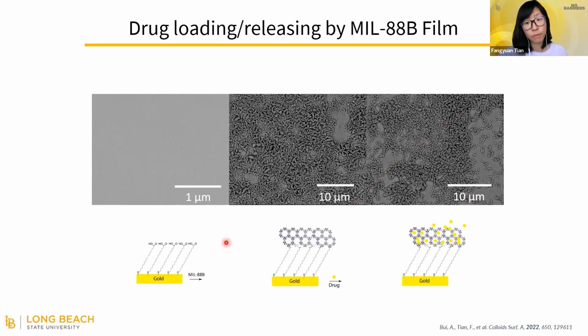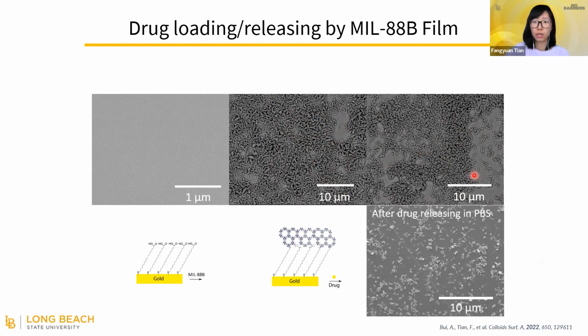We also used scanning electron microscopy to look at the morphology of the surface after each modification step, starting from the self-assembled monolayer coated gold. It's relatively smooth and flat. After exposing the surface to MIL-88B, you can see lots of crystals attached to the surface. Each individual particle is around 500 nanometers. Even after the drug loading process, the majority of the crystals didn't change much. That means the drug loading doesn't affect the structure or the morphology of MIL-88B. But after we expose the surface to PBS solution, lots of those crystals were washed away or started decomposing.